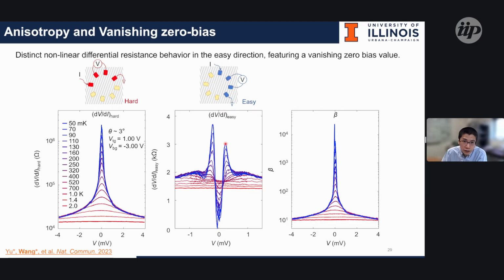But with the external bias along the so-called easy direction, or along the quasi-1D structure direction, you are seeing such a superconductivity-like behavior, which means that sometimes when you see superconductivity-like differential conductance, it might not be superconductivity. It could also be a collective behavior of a strongly correlated system, indicating a strong collective excitation of such quasi-1D systems.